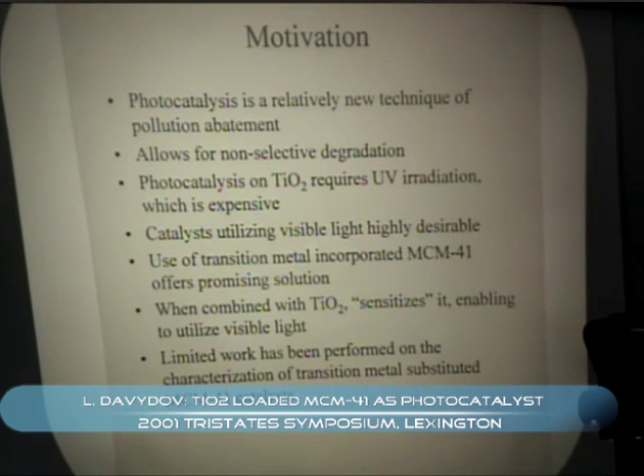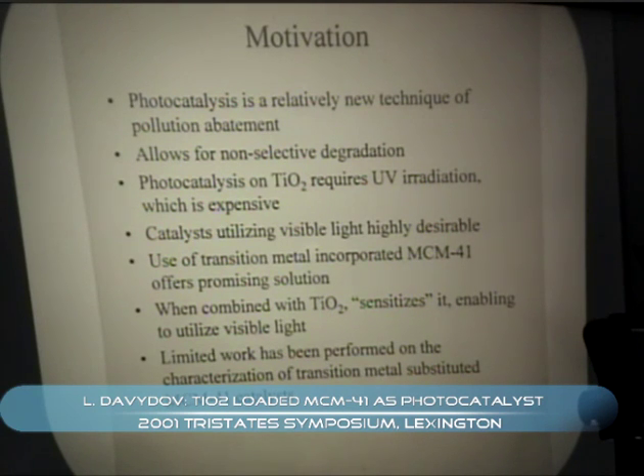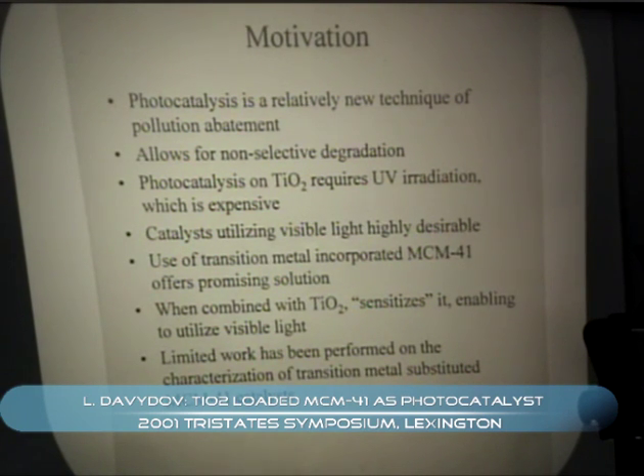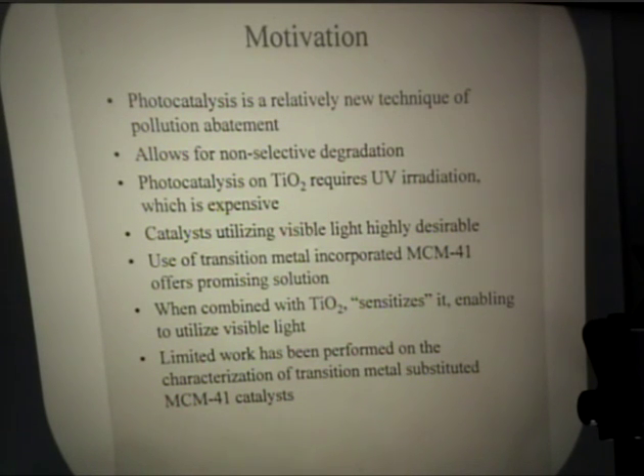The advantages of this method are room temperature operation, complete oxidation to CO2 and water, and it is non-selective. However, the best and most studied photocatalyst TiO2 requires ultraviolet irradiation, which is expensive and harmful to humans. Therefore, it would be desirable to make a catalyst capable of utilizing visible light, which doesn't require special sources of radiation and is benign.